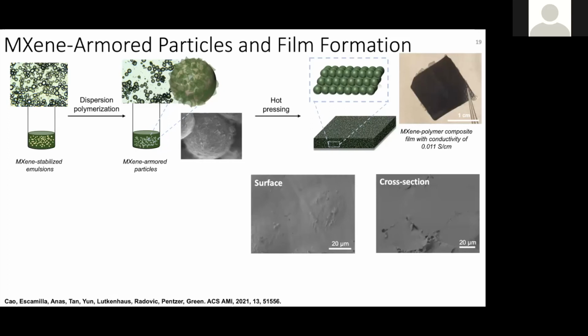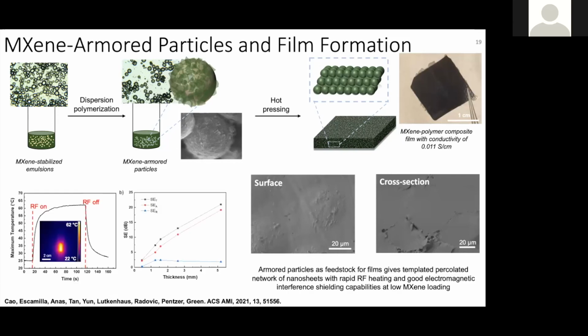We see the particle, the residual morphology from the particles. And we showed that these underwent, because of the conductivity of the MXenes, rapid RF heating and could also be used for electromagnetic interference shielding.